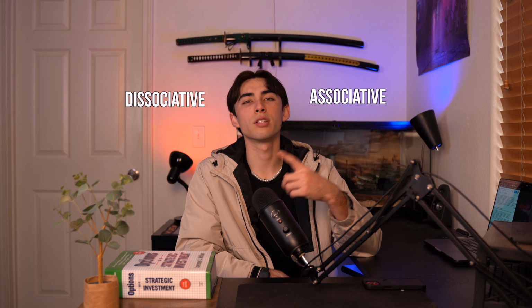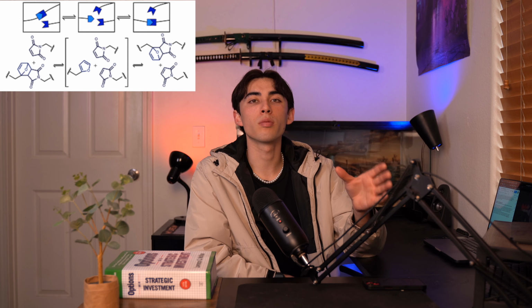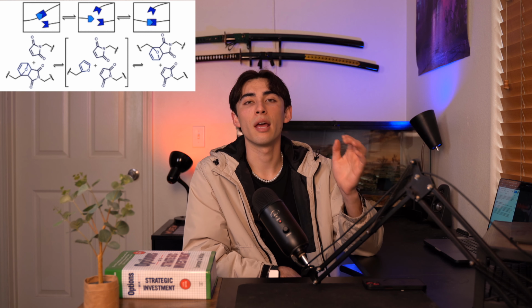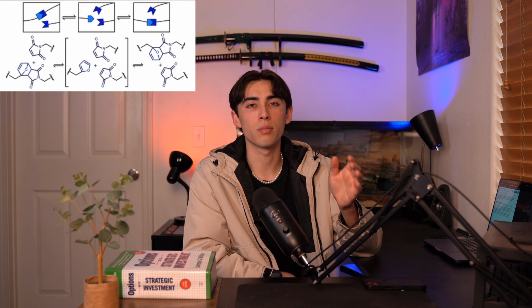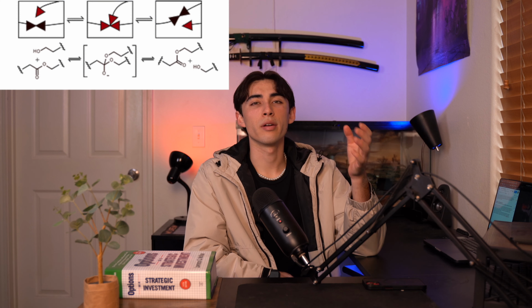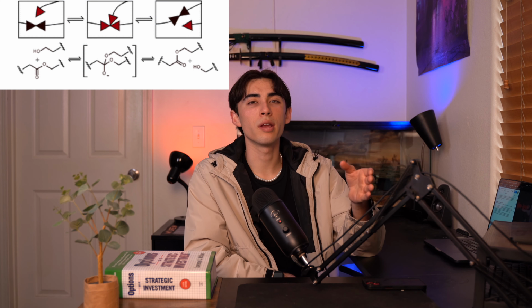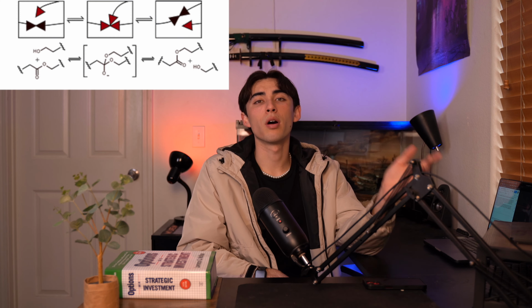CANs can be classified into two different groups, associative and dissociative bond exchanges. Dissociative CANs are where a complete bond rupture occurs upon heating, and then the bond subsequently reforms upon cooling. This reversible cleavage of bonds within the network leads to a decreased cross-link density. Associative CANs, on the other hand, are networks in which bonds are only broken when new ones are formed. This bond-forming, bond-breaking sequence occurs without a change in cross-link density or a decrease in connectivity.